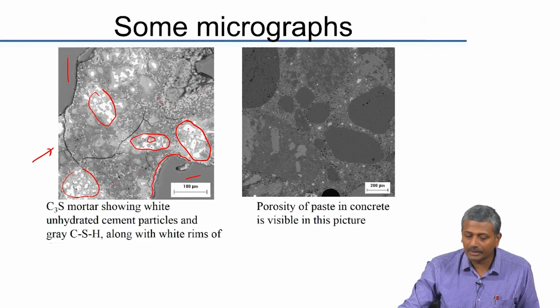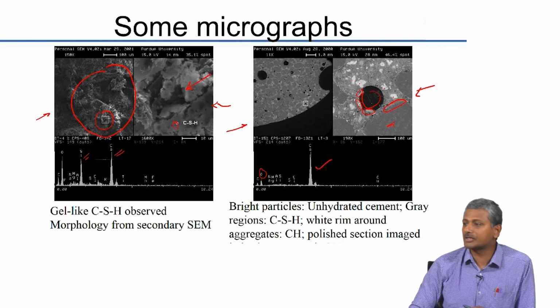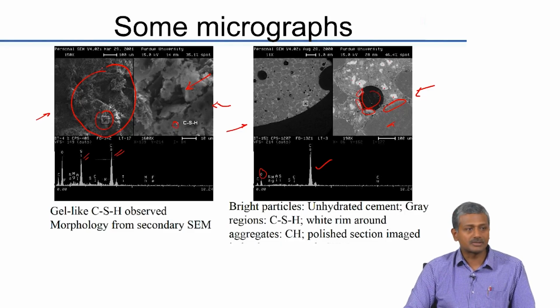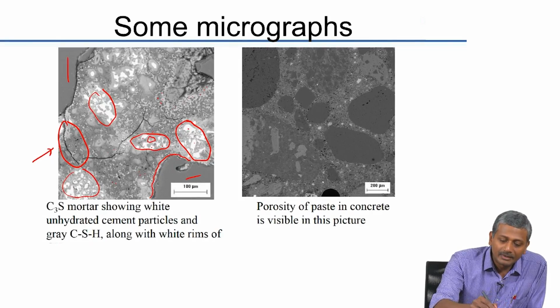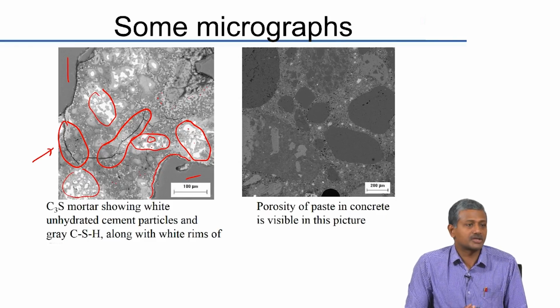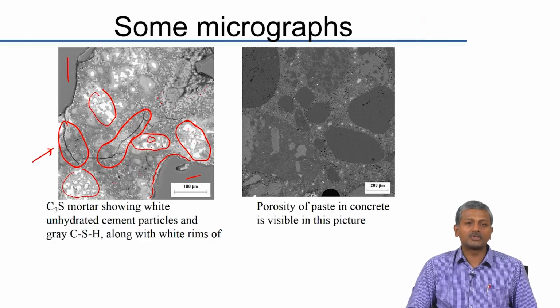When you see, like in the previous slide, you actually see the morphology. Look at this left side image. You can actually see the gaps and crevices and the flaky and fibrous crystals. So that's actually a fractured image. You see that there are cracks here. Okay, that cracking may be shrinkage cracking, we don't know. The cracking also may be because of specimen preparation for the SEM.